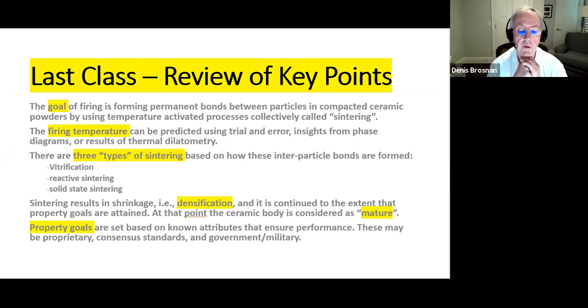Another type of sintering also forms a glass. It's called reactive sintering, but during the process of sintering, that glass changes in composition and forms crystalline matter. So gradually during firing, the bond in the ceramic changes from glassy to crystalline, and the glass may partially or wholly disappear during that form of sintering.